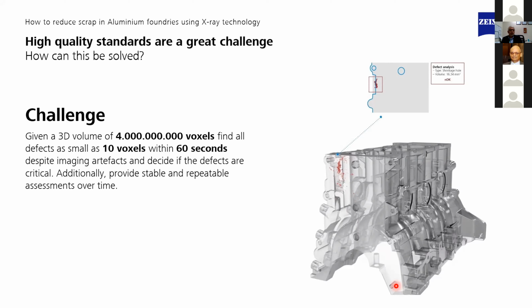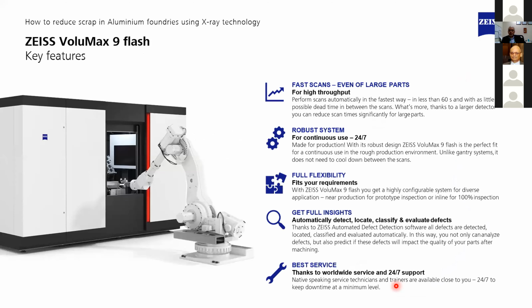And here, if we talk of inline, the cycle time requirements sometimes range between 45 seconds, 60 seconds to 1 or 2 minutes, depending on the requirement from the customer. So if you have to take a decision in 60 seconds, and you have to analyze 4 billion voxels, it's a huge amount of data. But we have developed certain software features, with built-in artificial intelligence, by which we are able to accurately pinpoint the defect, its size, as well as orientation and dimension.